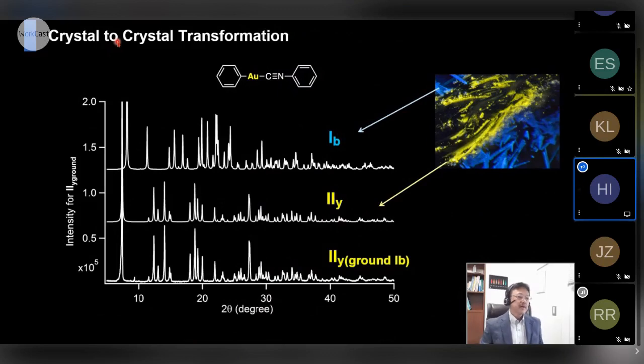The previous gold complex shows a crystal to amorphous structure change, but this complex shows a very different structure change. This complex shows a crystal to crystal change. So this is the XRD analysis result of the blue colored crystals and the yellow one. The previous compound in the first movie shows an amorphous state, but in this case, it is also crystals. And the other different thing is that this structure change was very rapid. In the previous case, maybe some part of the structure change was rapid, but the complete structure change to amorphous was not so rapid. But in this case, the crystal to crystal change was very rapid.